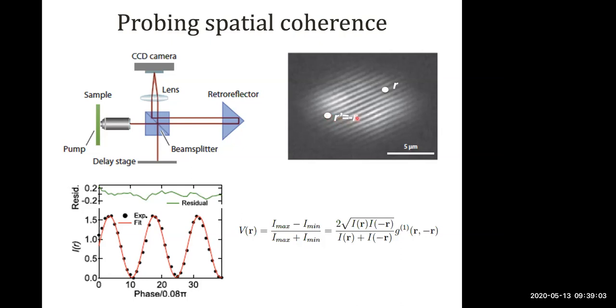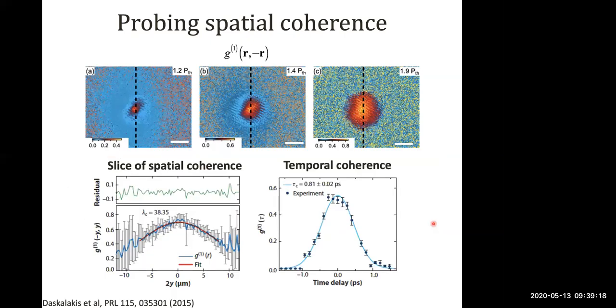And in that interferogram, each point at, let's say, R tells us about the phase coherence between this point and the point at R prime, which is centrally symmetric. So R prime here would be minus R. And by moving a delay stage, we can quantify the visibility of these fringes and quantitatively extract the degree of first order coherence, G1. Okay, so this was done in TDAF as a function of the pump power. What you find is that G1 increases in both space, so coherence length, and in the absolute value as you increase the pump power. And at a power of about twice threshold, the coherence length is nearly 38 microns, which is much larger than the pump spot itself.